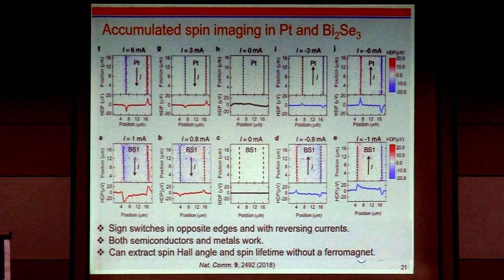If you look very carefully, in the middle of the channel, platinum gives almost zero signal. This is expected because my measurement only couples to spin up and down. But in principle, in the middle of the channel, we should have an in-plane spin component, which I cannot measure here. But now if you look carefully in this case, bismuth selenide, I can see there is a shift downward, kind of bluish here. But if you look at this one, there is a shift a little bit upward, kind of reddish signal.